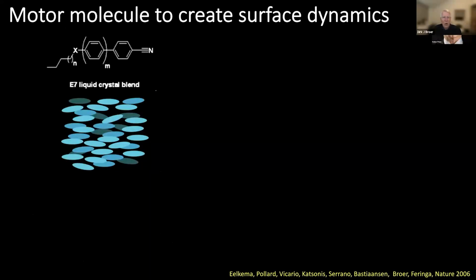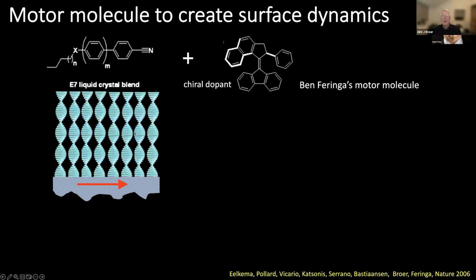And this was early work that we did together with Ben Feringa, well known, I assume, within the world of molecular motors, where we took a liquid crystal blend, and to this liquid crystal blend, we added the chiral dopant, the motor molecule of Ben. And because of that, the uniaxial alignment of the liquid crystal is converted into this helicoidal alignment, with helices with the axis oriented perpendicular to the substrate.